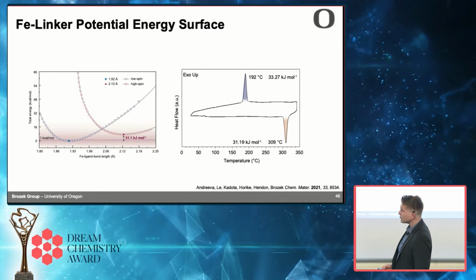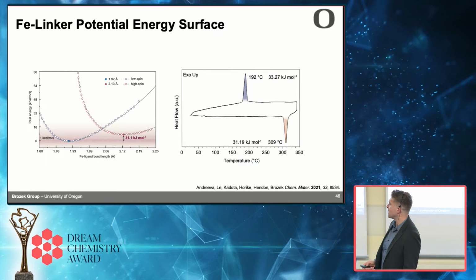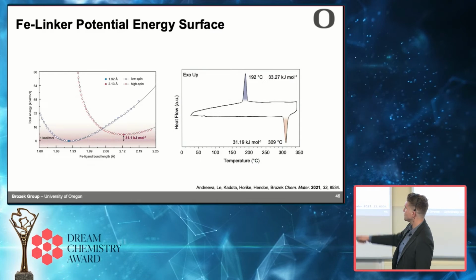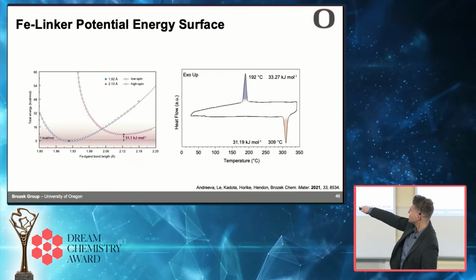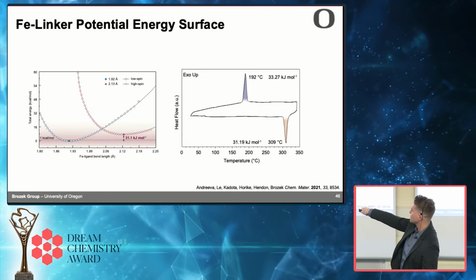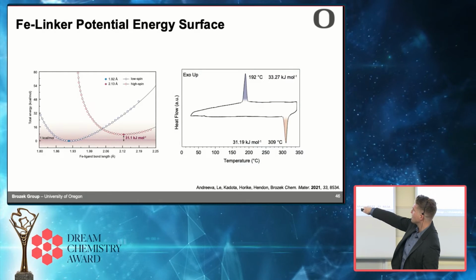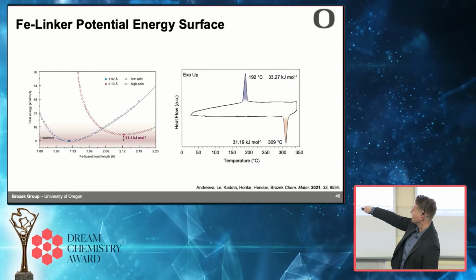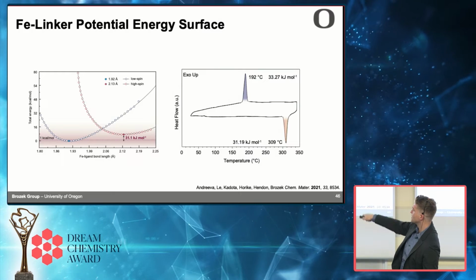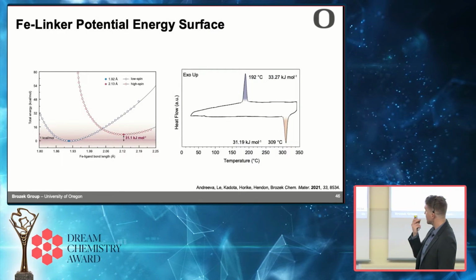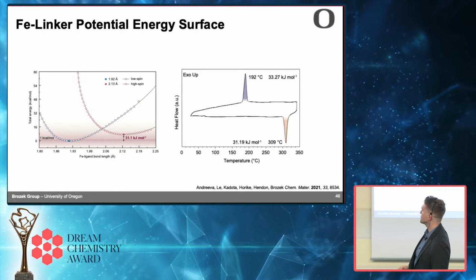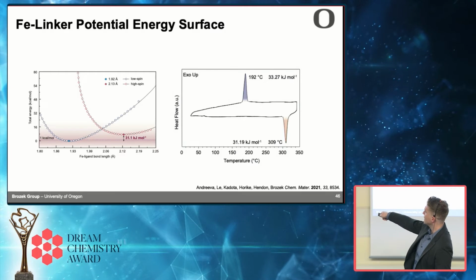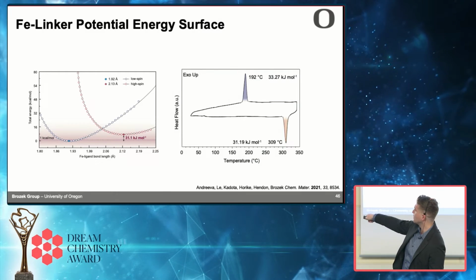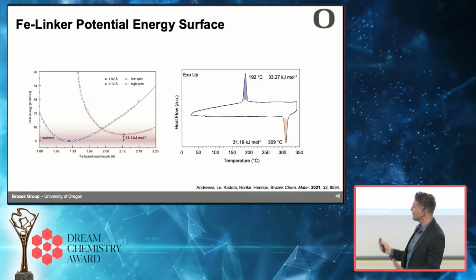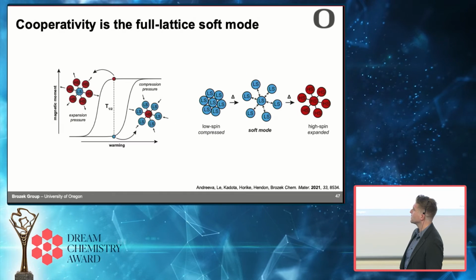And we can predict the energetics of the spin crossover in iron triazolate. Here's the potential energy surface for the low spin. Here's the potential energy surface for the high spin. We predict that they should be different by about 30 kilojoules, so delta H should be about 30 kilojoules. When we measure the spin crossover using calorimetry, we get spot on for about 30 kilojoules per mole. So this is all nice. So we think we understand this material.